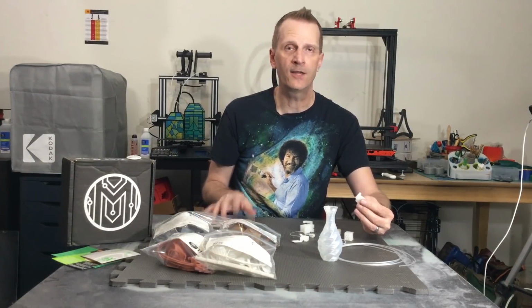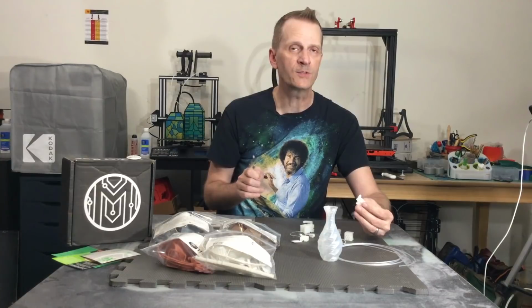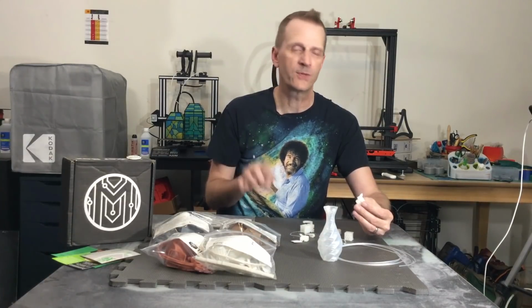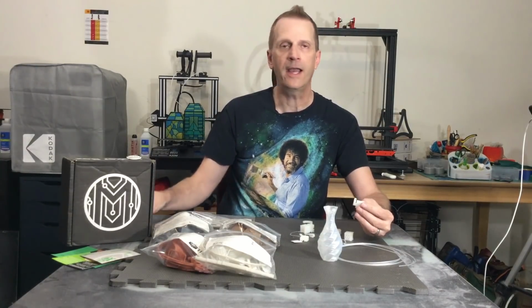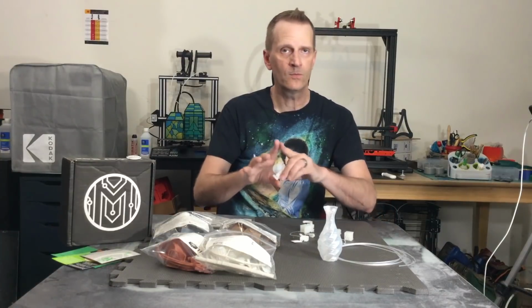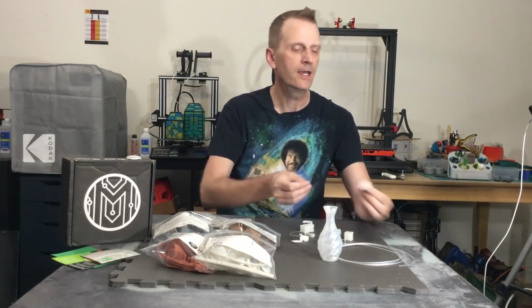228 degrees C on the hot end with a cold bed, 40 millimeters per second, 3 top layers, 3 bottom layers, 3 perimeters, 20% infill, and not using anything, glue stick or anything, just sanded acrylic, and it did not stick.